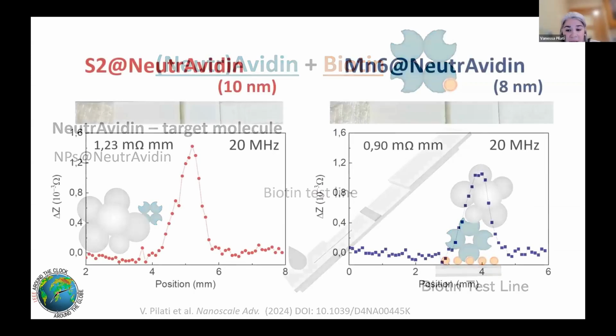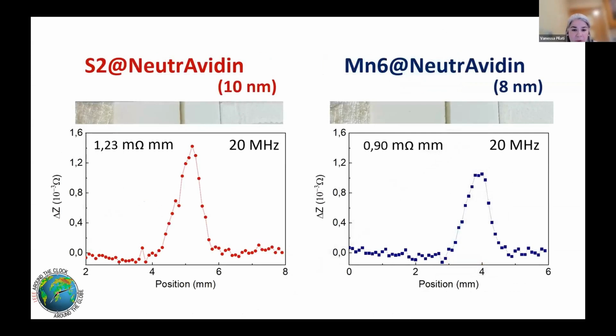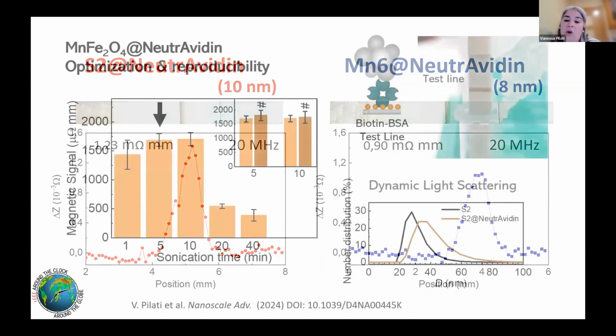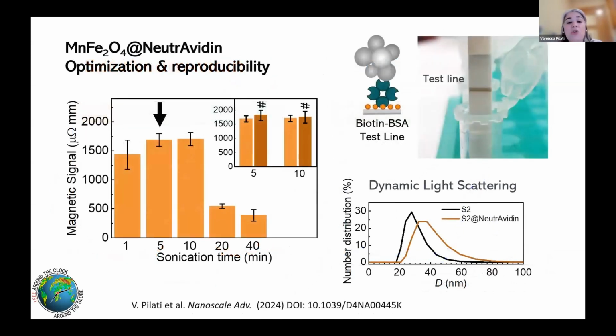So we did this using the same parameters, same protocol, and we saw that the nanoparticles with large diameter provided a large magnetic signal as expected. So we decided to go further with these nanoparticles because they are more sensitive for detection.